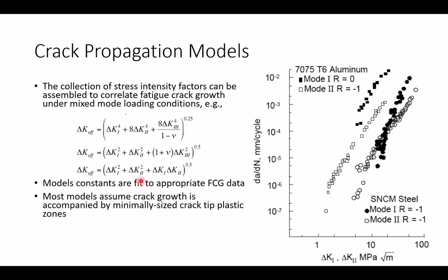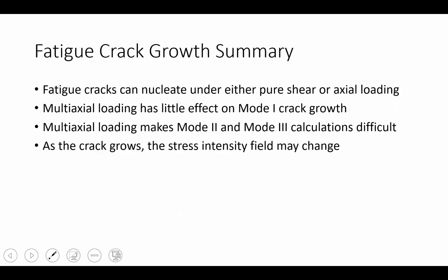The models are fit to fatigue crack growth data and most models assume crack growth is accompanied by minimally sized crack-tip plasticity. Summary for fatigue crack growth: fatigue cracks can nucleate under either pure shear or axial loading. Multi-axial loading has little effect on mode 1 but makes a big effect on mode 2 and mode 3, and the calculations are difficult. As the crack grows, the stress intensity field may change because the crack can turn, changing its trajectory and direction.